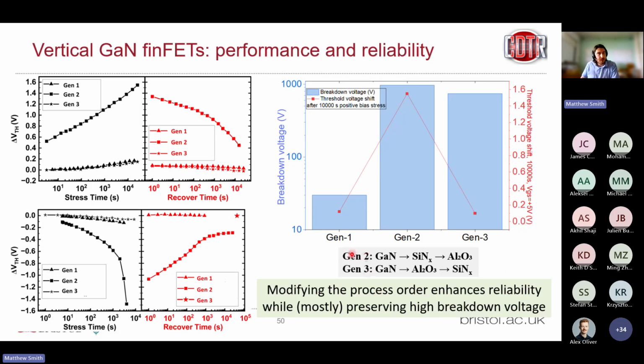But in terms of our stability, it's really, really enhanced compared to those generation 2 devices. So we can see here the generation 3 is basically mapping on top of those generation 1 devices. So when we stress the devices, they're not degrading in the same way as those generation 2 devices were. So this plot summarizes that.